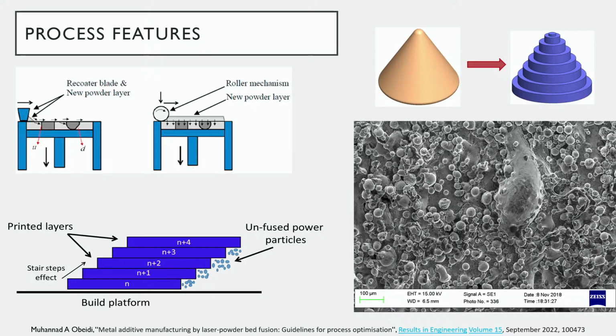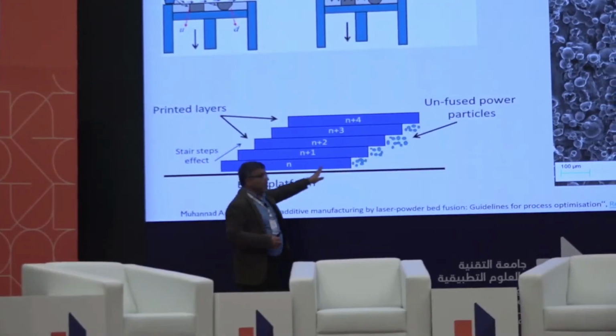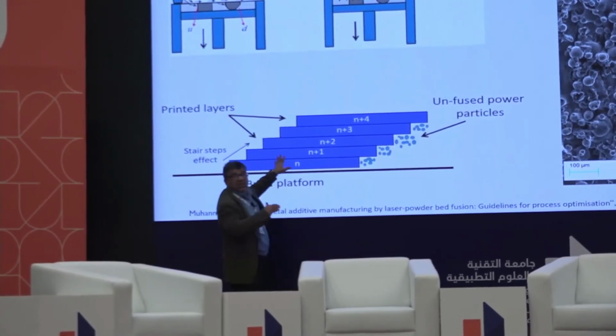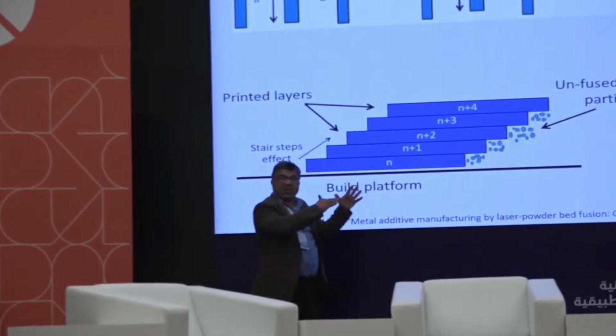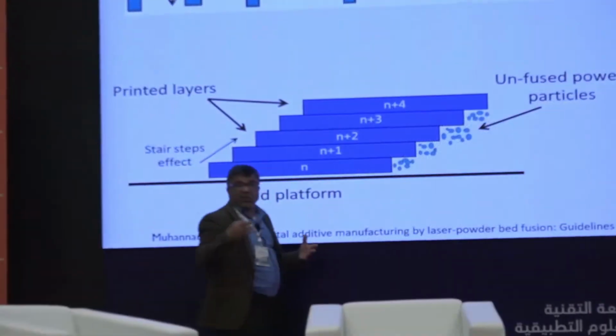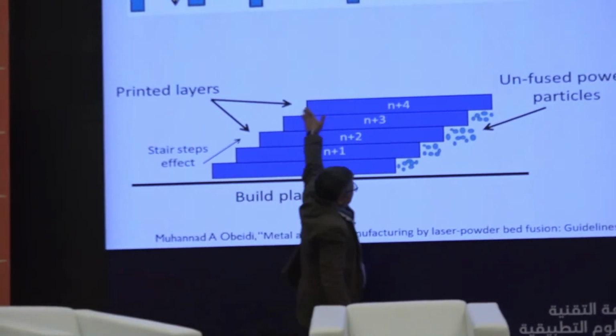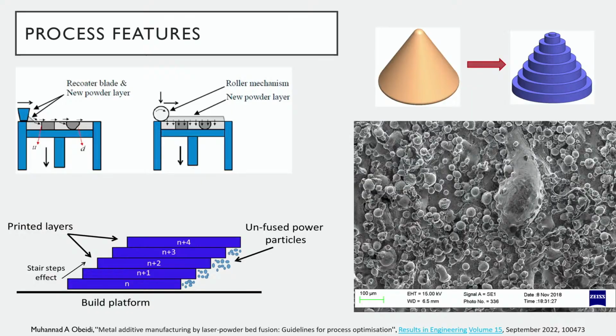Yeah, thank you. So during the print, why do we have surface roughness? Say I printed the first layer, number n, and then proceed to the top. Imagine this part is a feature in a mechanical part. This can be like a cross-section of a tube. So this is the outer diameter, and this is the inner diameter. That part, the pyramid, how do I print it? It's like that. So we print layers, and as we proceed, we make the layers different in length. So one layer is shorter than the other one, and here it's longer because it's a tube.